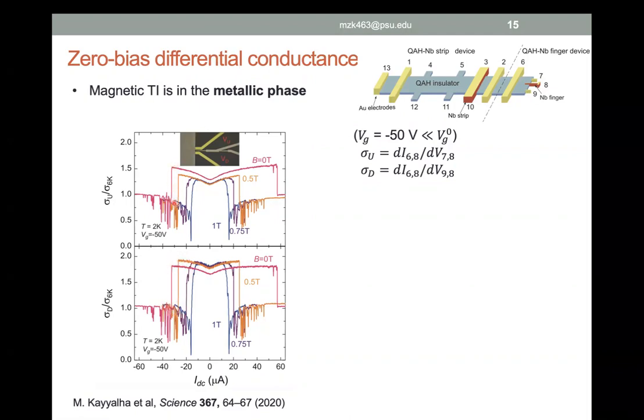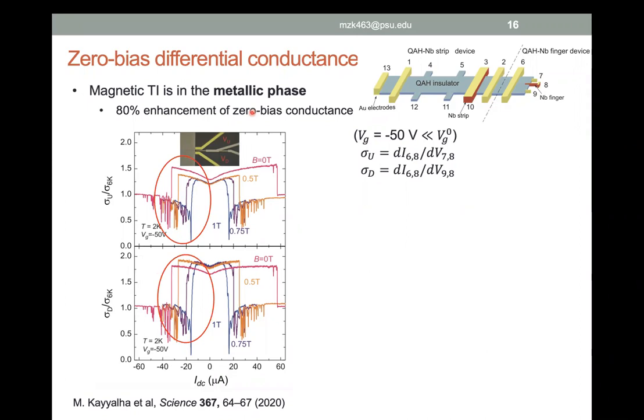But the resistance value that we see here is actually very large. So the change in the resistance is several kilo ohms, whereas the niobium finger resistance is several or hundreds of ohms. So this change in the resistance cannot be due to the superconducting to normal transition of the niobium finger. It has to come from the interface because it is much larger. So we see around 80% enhancement in the zero bias conductance. So we know that there is some sort of Andreev reflection going on in these samples. So the superconductor not only is superconducting, but it's providing relatively good contact to the quantum anomalous Hall insulator.